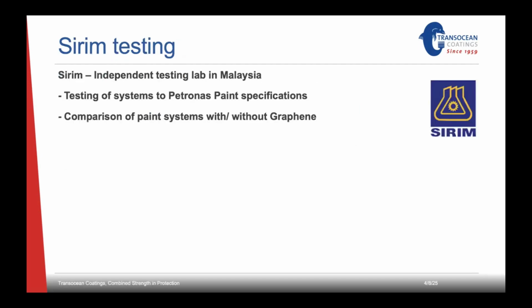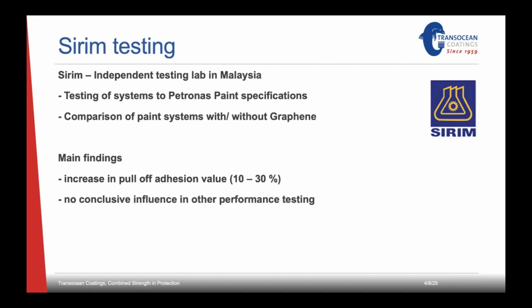Sirim is an independent testing lab in Malaysia. What they do is test paint systems of various paint companies to the Petronas paint specifications. As Transocean, we were already approved by Petronas with several paint systems. So we compared the performance of our paint systems with and without graphene. The findings were interesting because although we see a positive effect on the performance testing, we cannot really say it was conclusive. Maybe the existing paints were already very good, of course. But we did see an increase in adhesion values by 10 to 30%, dependent on the system. So that was the Sirim testing.